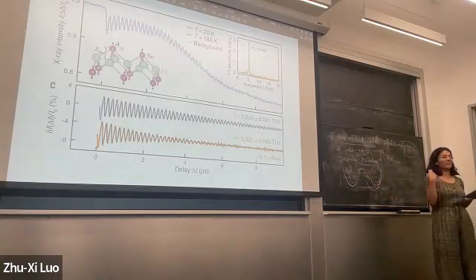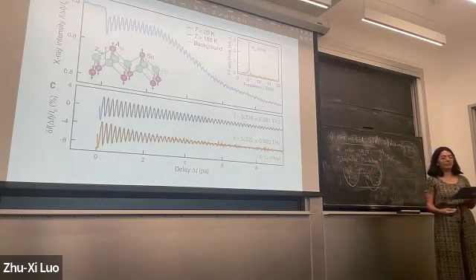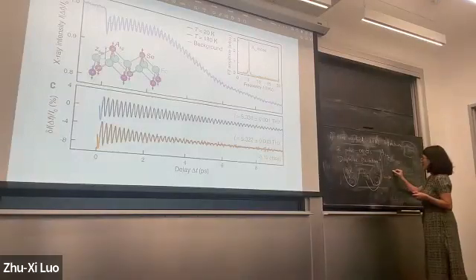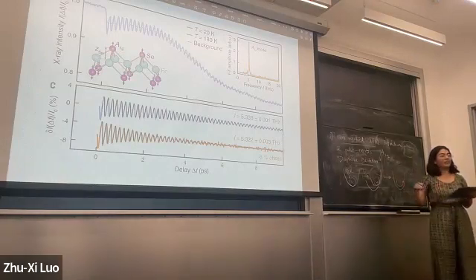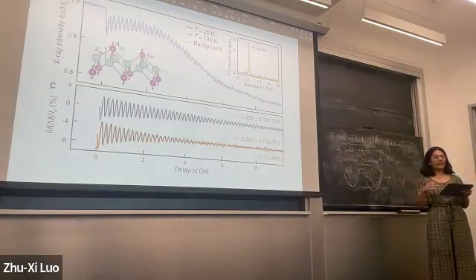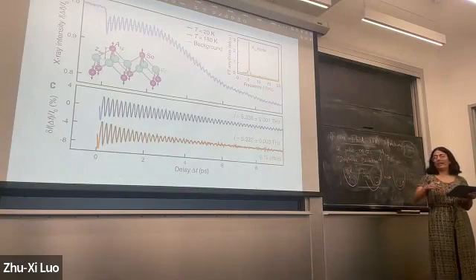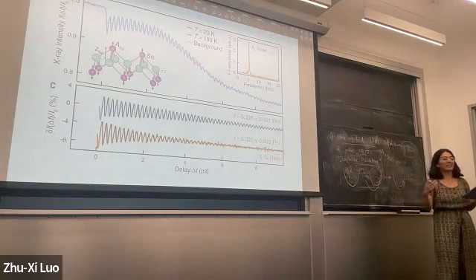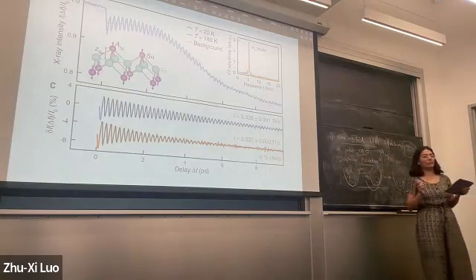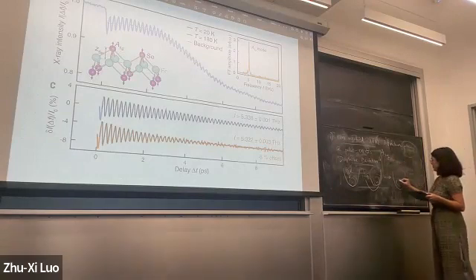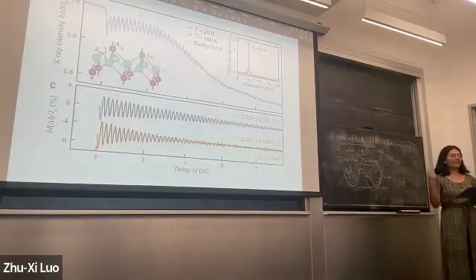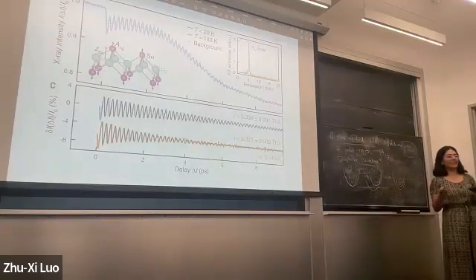But because this pulse happened so quickly, it doesn't have any time to adiabatically go to the new minimum. And so what happens is that you get this oscillation about the new equilibrium, but it will be damped as the system relaxes back to the old equilibrium and various other thermal processes. This is the main idea of why we expect this IR pulse to excite a phonon in any way.